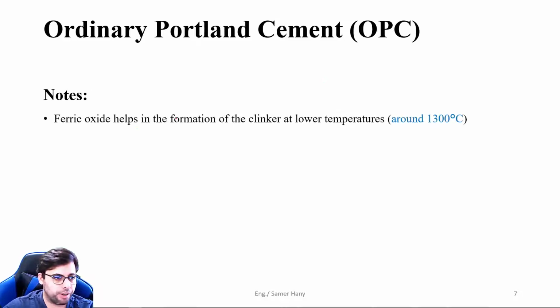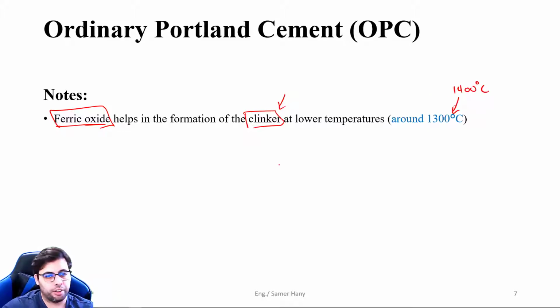Okay, so some notes here. The ferric oxide additive helps the formation of clinker. The clinker we'll discuss later in a couple of minutes, which is the intermediate product in the cement production process. So it helps the formation of clinker, which is formed in the main reactor in the factory at lower temperatures, around 1300 degrees Celsius. Normally without ferric oxide present in the mix, this reaction will be at 1400 degrees Celsius instead of 1300, and this of course saves us some energy and some fuel and some cost when producing the cement.